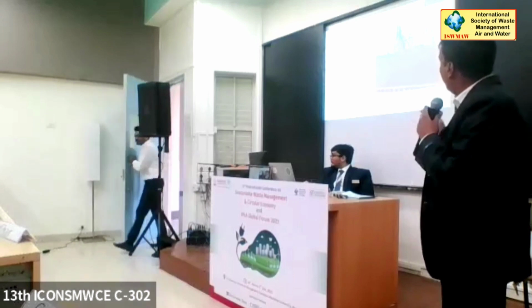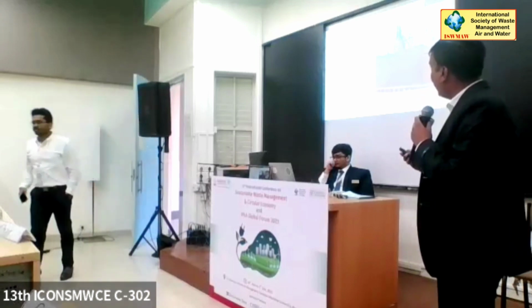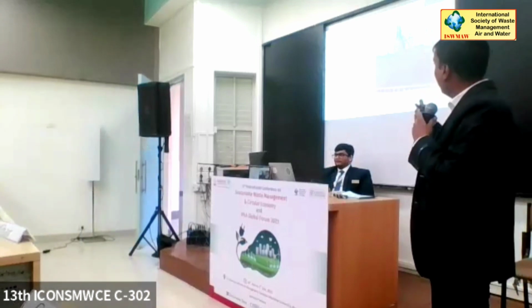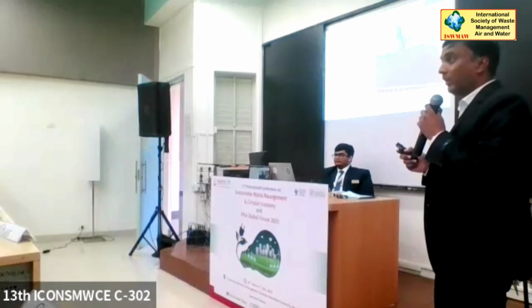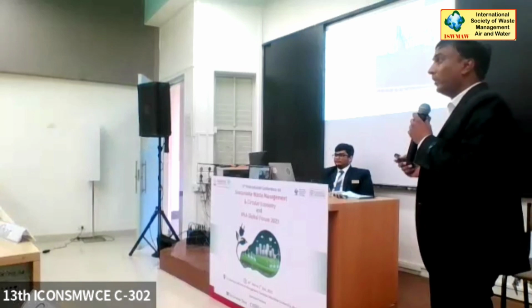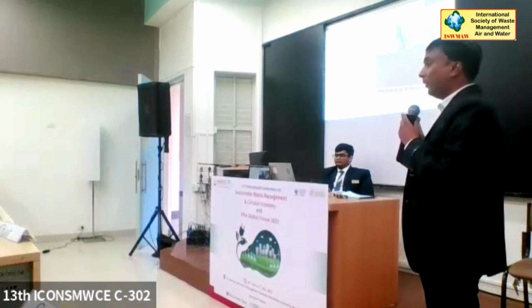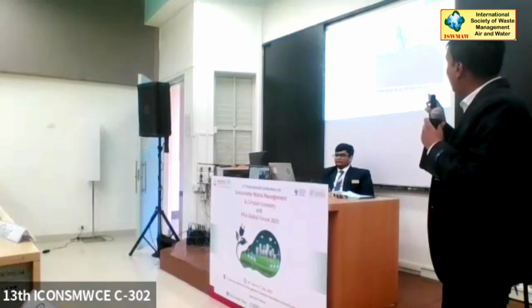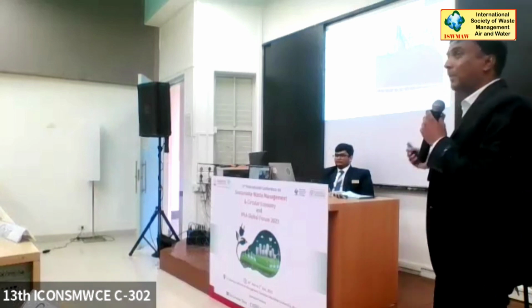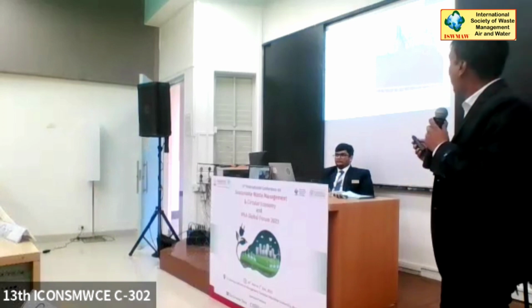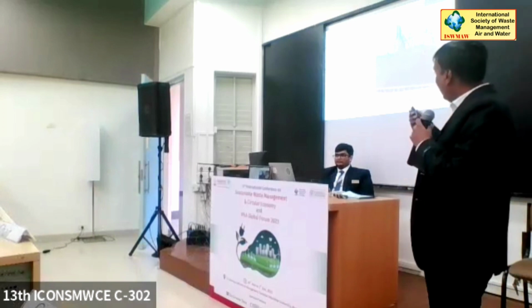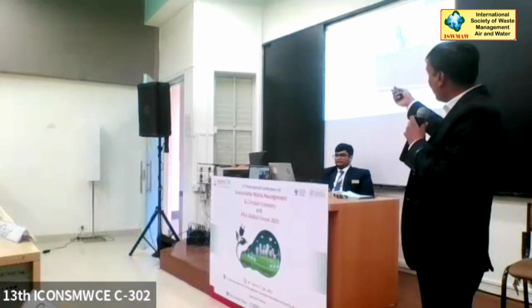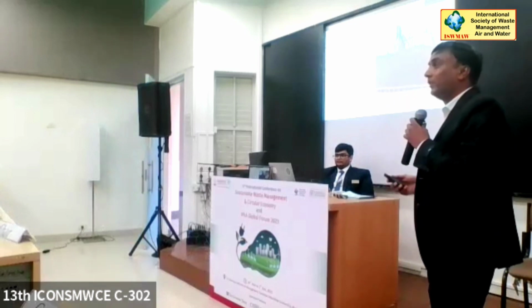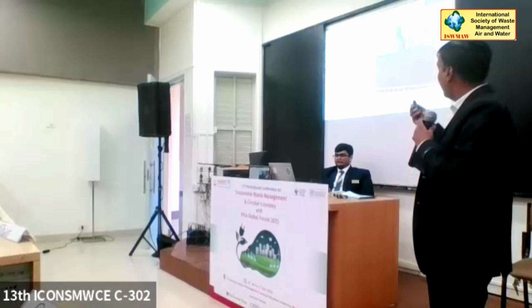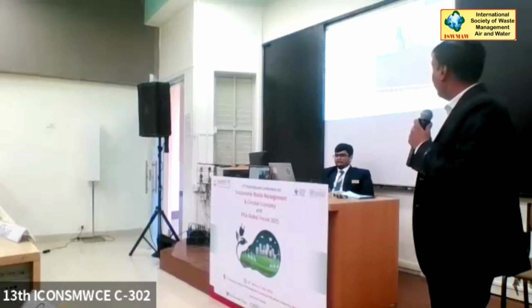Now look at the utilization of slag. As I have already told that we are replacing red ochre. Earlier we used red ochre as a natural mineral. Now we 100% replace this red ochre with slag. Slag is a byproduct of Hindustan Zinc Limited. And if we see chemical analysis of slag, 35.3% is alumina content. So this is helpful in maintaining our liquid content.